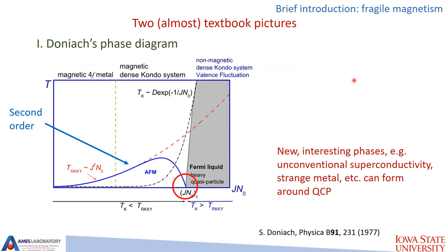There are two basic textbook pictures related to what I will be talking about. One of them is Doniach's phase diagram. So you have a metallic antiferromagnet with two competing interactions: the RKKY interaction, which gives you magnetic ordering, and the Kondo interaction, which gives you screening of your moments. Depending on where you are, and this is a phase diagram from many years ago, either magnetic order wins or Kondo wins, and you are suppressing magnetic order. Now, this transition is second order all the way. This is the quantum critical point. Right here, sometimes interesting things happen. You can have superconductivity here. You can have a strange metal here. You can have Fermi liquid, and often you do, in this part of the phase diagram.